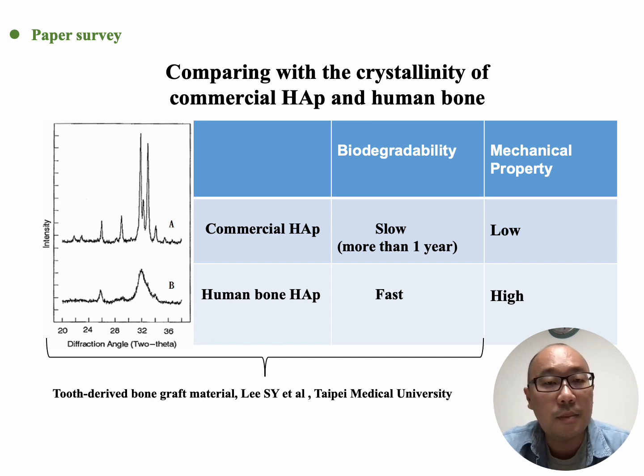For the commercial hydroxyapatite, it will have higher crystallinity, and the disadvantage is the biodegradability will be very slow, and the mechanical property will also be lower. But for the human bone hydroxyapatite, you will get fast biodegradability, it's compatible, and the mechanical property is higher. So it's totally different. For the XRD, the human bone has poor crystallinity compared to the commercial hydroxyapatite. It's synthesized at high temperature, so its crystallinity is higher than the human one.